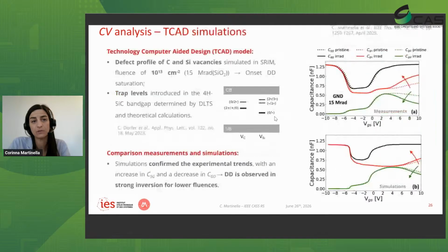And so then we simulated that. We considered a case with a lower dose, 15 megarads, which was the onset for the displacement damage, corresponding to about 10 to the 13 protons per centimeter square. That's where you can start to see in these measurements that there is this modification of the capacitance value. So you start creating defects that trap your carriers.